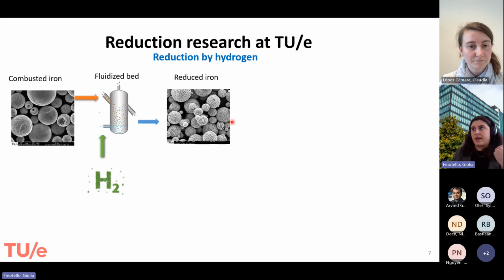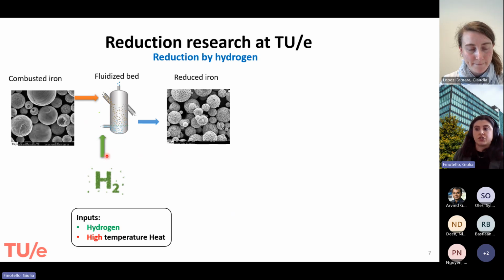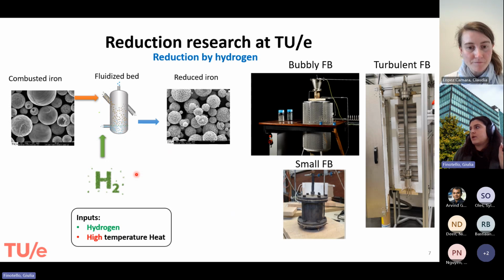First, we are doing a reduction with hydrogen in a fluidized bed. We are feeding combusted iron that you can recognize here from its very spherical shape, very solid. What we produce is similar to the DRI picture that you've seen before, a very porous solid particle. In this case, what we need is hydrogen and high temperature heat. I'm talking about temperatures between 500 and 900 degrees Celsius. And here we have some of our fluidized beds at the university of different scale and type.